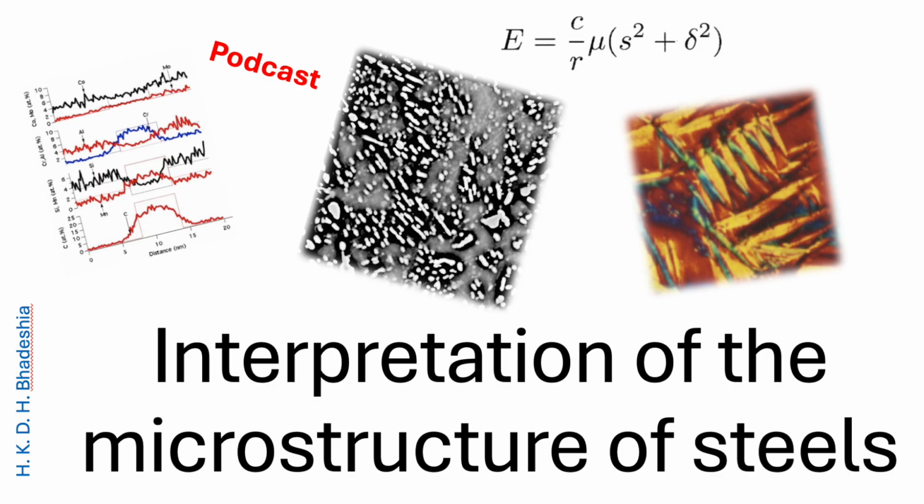It forces the trapped carbon atoms out of that supersaturated lattice. And they form precipitate. They precipitate as fine cementite particles. And that lowers the energy and increases the toughness, all without destroying the overall hard structure.